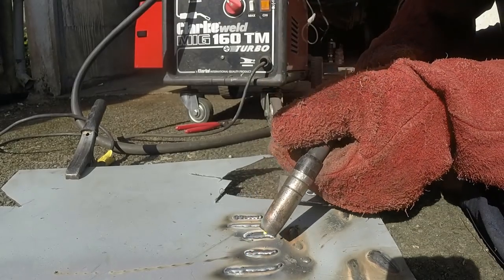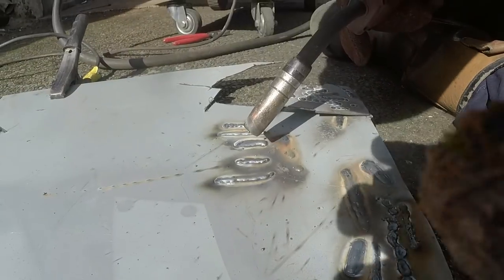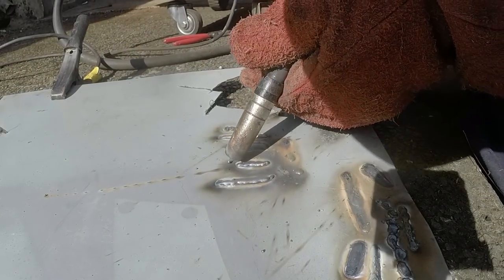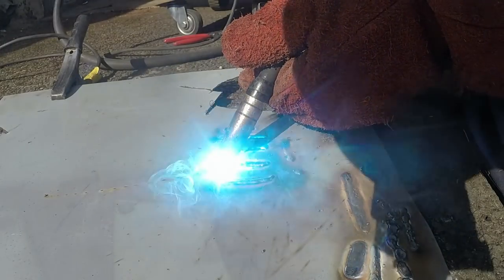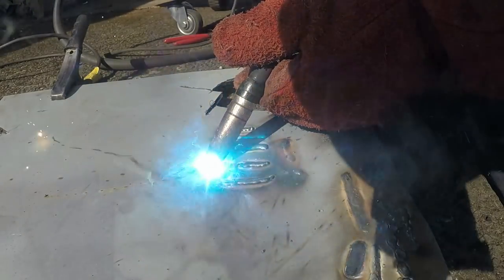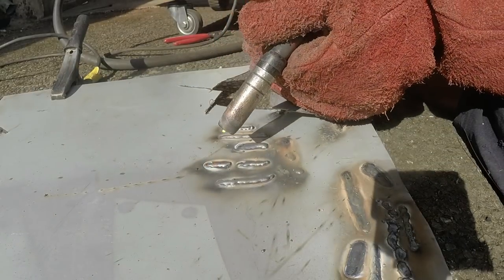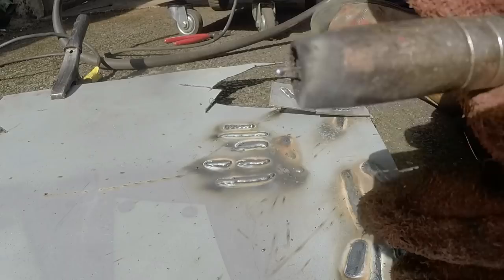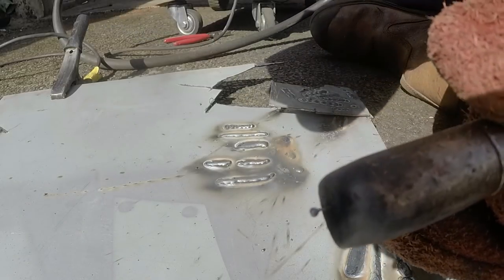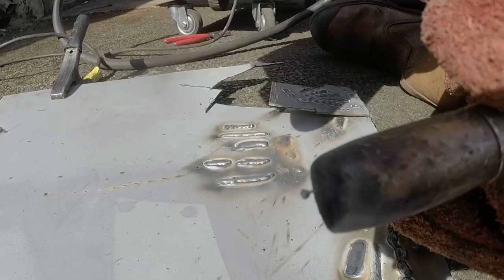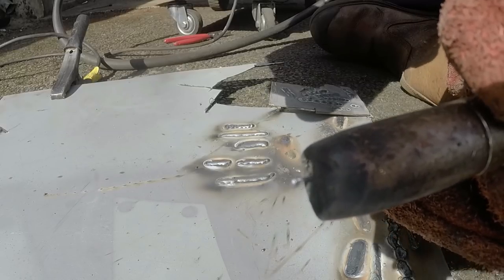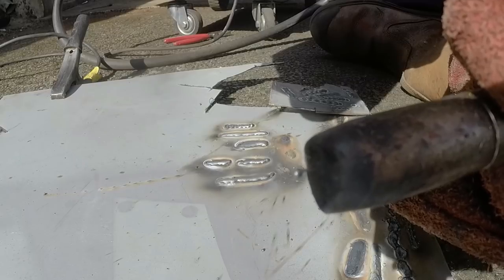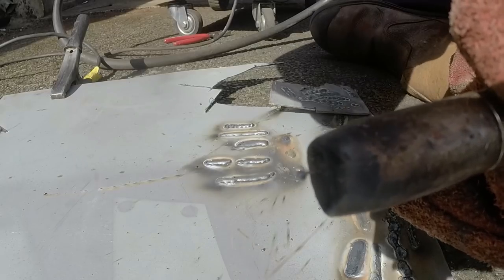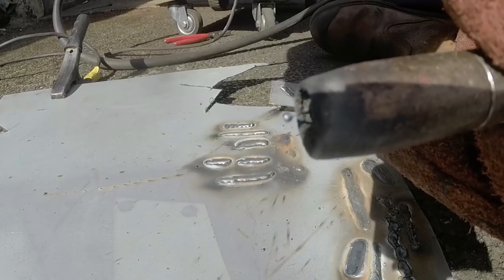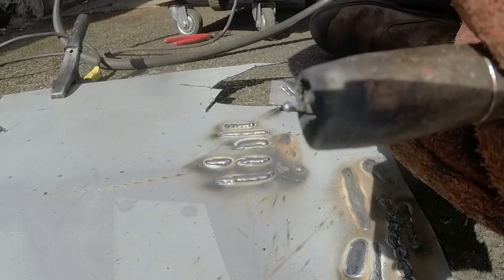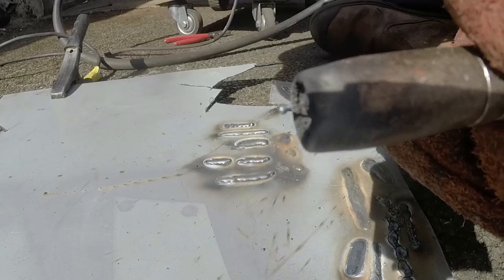So I don't know how that's showing up on the camera, if I've even aimed it at the right place. I'll do it again. So I can see through the goggles that actually what's happening is I'm getting individual balls of weld like that forming on the tip of the wire, because it's making contact with the surface. The circuit is being completed. It arcs and burns the wire back up into the gun, breaking the arc, and then the whole process has to start again as the next bit of wire gets delivered to the surface.